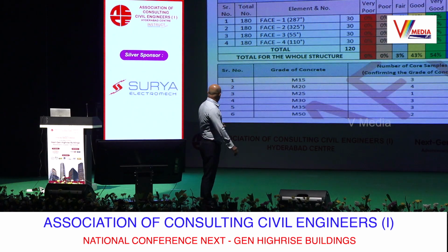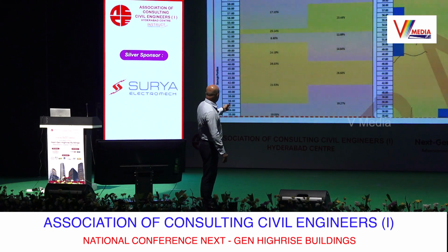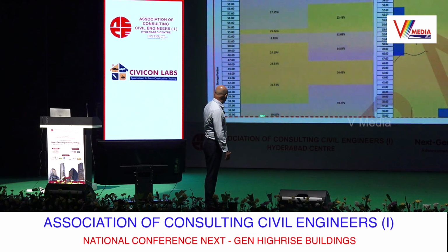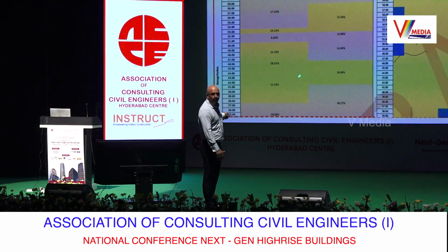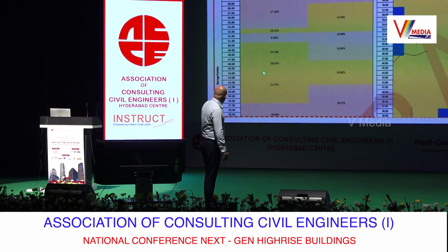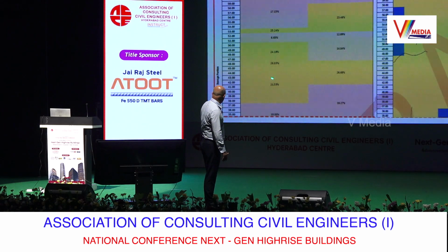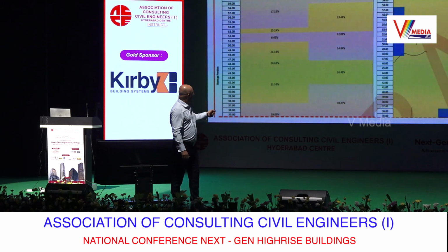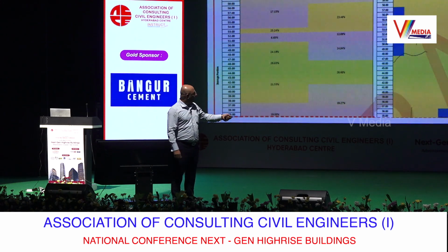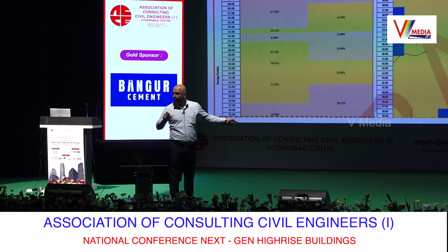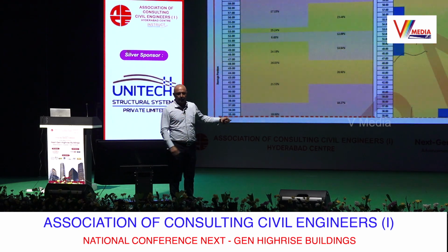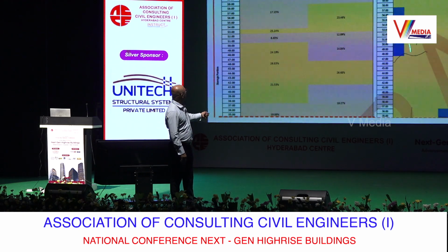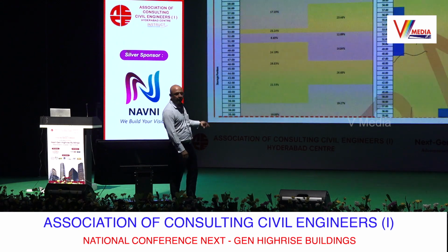Hoop reinforcement. So we did GPR, and these are the results, this is the storage portion, the non-storage portion. This is the apex of the cone, and this is the area where your pressure will be maximum. You can see 23%, 26%, 30%, 24%, all the deficiencies were majorly in this zone. As a result, those cracks were coming. And you can see all the repaired patches had turned hollow. They were sounding hollow, so they had debonded. These are the results of the NDT and other tests, so we are correlating all three.